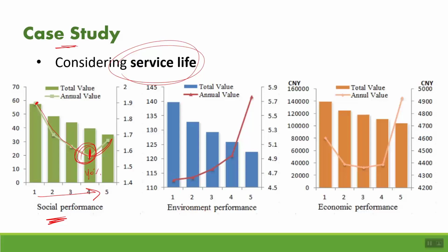But for the environmental performance, as can be seen, by increasing the fly ash replacement ratio, the environmental impact is increased. This can be explained by the use of plasticizers or water reducers when using fly ash, so as to increase the workability of concrete. Water reducers have a very high environmental impact, which causes the environmental impact of concrete to increase, which worsens its sustainability performance with time.